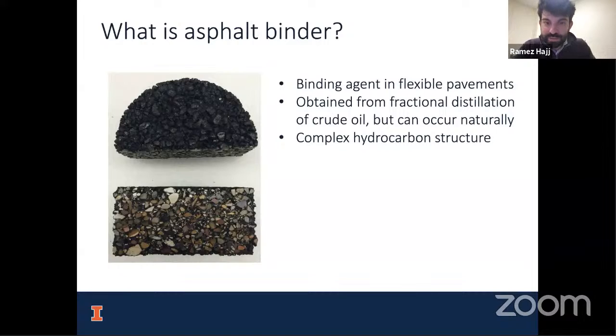But asphalt binder looks quite different. It has a huge geographic variation, and this is because of its complex chemical composition. So I won't get into too many details, but the important thing to take away is that asphalt binder in general, every single binder is different. Which means every single mixture is different. No two are the same, even if that binder is sourced from the same source. Actually, different batches from the same source will still have differences. So it's very critical for us that we're thinking about the complexities associated with the chemical composition and how to properly know what type of binder we want to use.